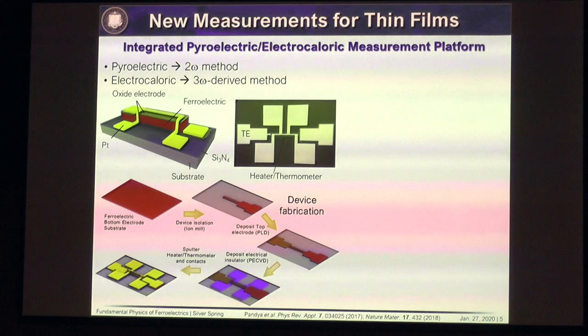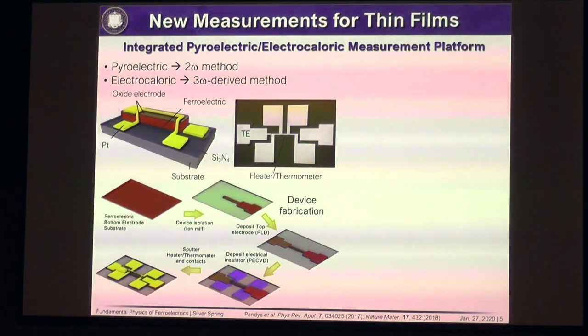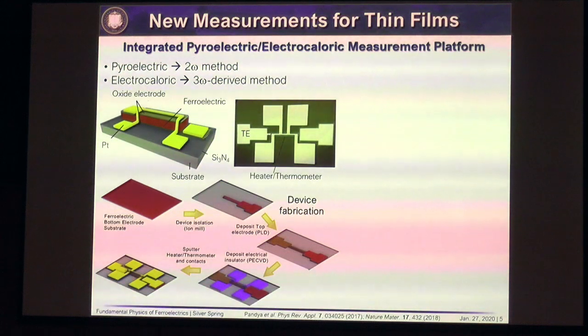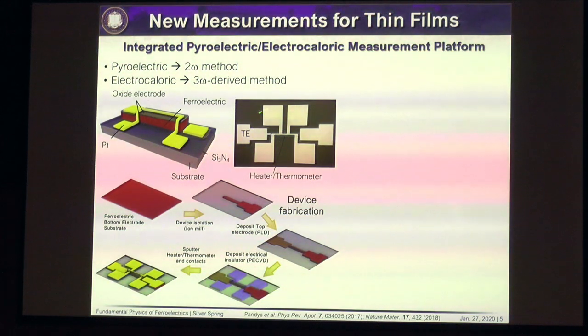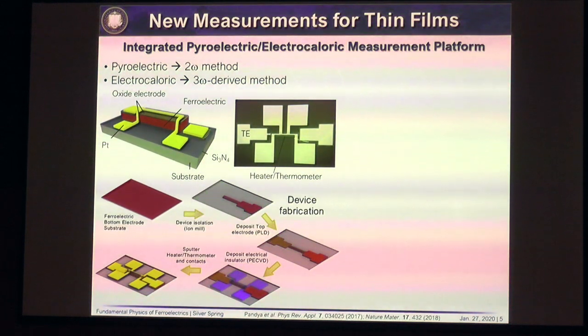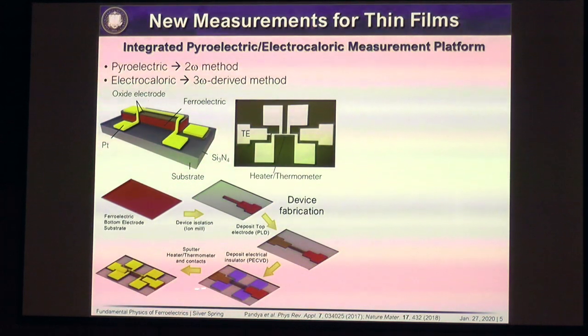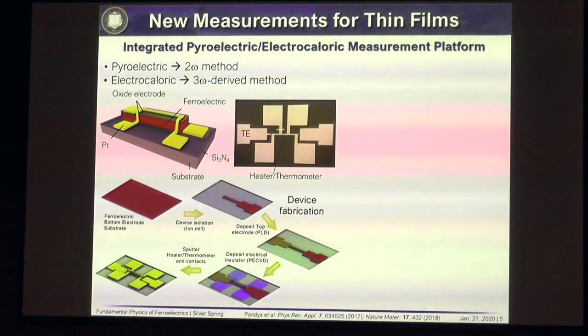So what you ultimately do is you create little capacitor structures of your thin film materials with these integrated structures on top of them. This is a microscope picture of these real things. If you had done thermal transport measurements, this would look a heck of a lot like a 3 omega system. We just basically stole that same idea. So you can fabricate these device structures, and this allows us to either source